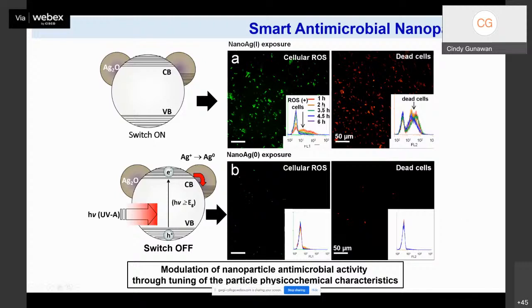As an extra slide here, I would like to show you this is the switch on nanosilver. As you can see, with the switch on nanosilver, it caused a complete growth inhibition. We could see a high level of cellular ROS generation here and a high level of dead cells. And this is the switch off nanosilver. You can see that the silver oxide deposit is reduced to metallic silver. We can detect only low levels of cellular ROS and therefore low levels of dead cells. Therefore, it is in agreement with the switching off of the antimicrobial activity.